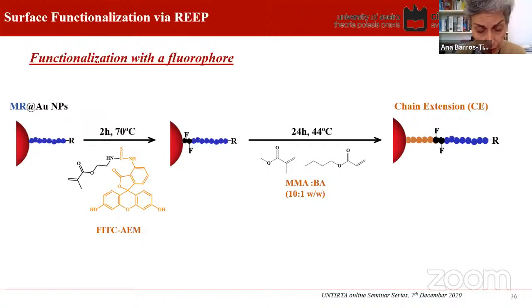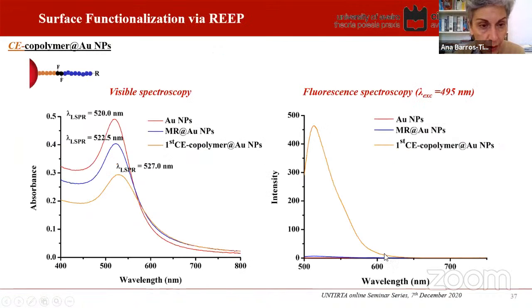that had been functionalized. And the idea was to later carry out the chain extension using the same type of monomers that were used in the previous strategies. We did that. We monitored the response of these materials via optical spectroscopy in the visible region and also via fluorescent spectroscopy. And clearly, the results after chain extension, described here as CE, lead to significant changes as one would want.